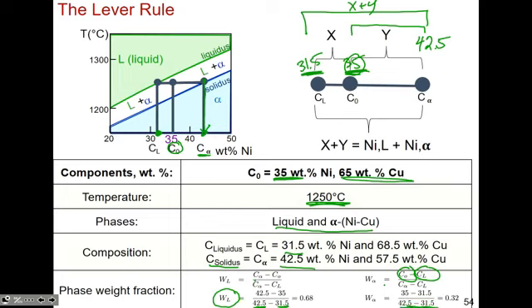So you could do these two calculations independently, but 0.68 and 0.32 should really add up to 1, right? You could have just stopped after doing this calculation and said, well, the amount of solid is just 1 minus liquid, because it has to add up to 1. So I'm not even going to bother doing the second calculation. Or you could do the second calculation as a sanity check and say, yes, 0.68 plus 0.32 is 1. Great. So that's how you would quantify it.